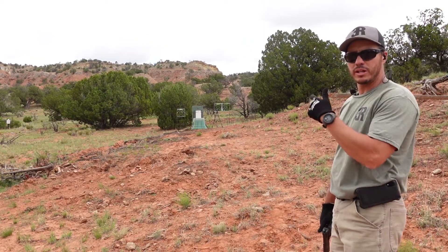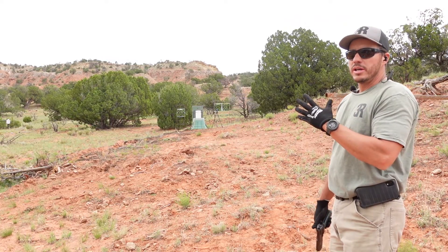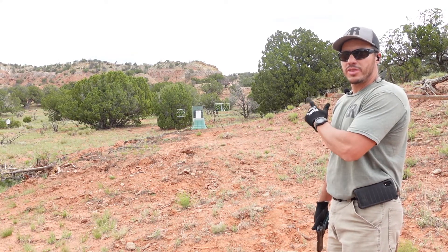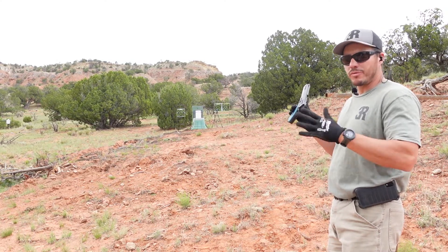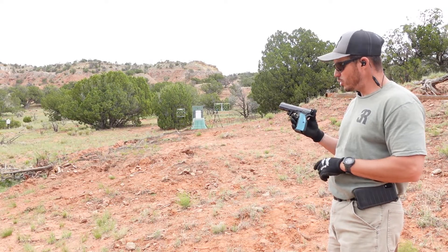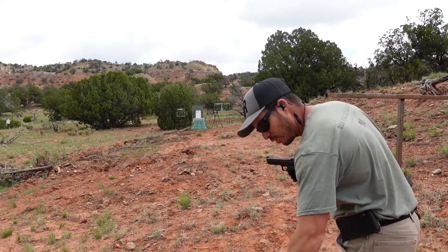We've got ballistics-grade ultra high molecular weight polyethylene out here — this is only 12 layers. This is basically to show you it may stop certain rounds, but there is quite a bit of force that follows through. Theoretically 12 layers should not stop 9 millimeter — it should take about 14 or so. We're testing this with a CZ Shadow 2, shooting 124 grain full metal jacket.